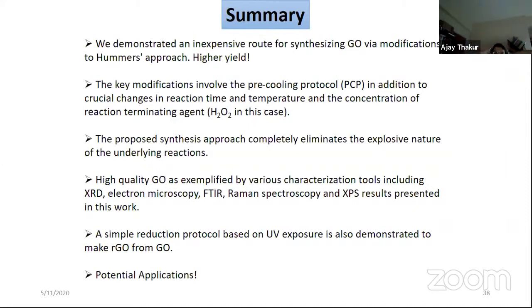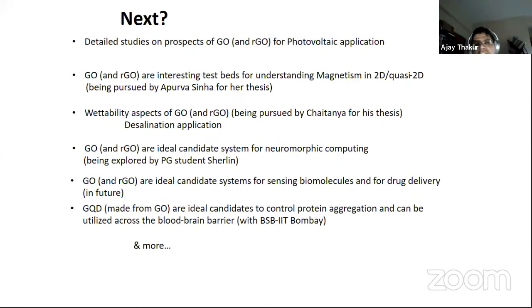Not only that, the Tour's method also employed highly expensive separation membranes or filtration membranes for preparing high quality graphene oxide. In our method, we could achieve high quality graphene oxide without using expensive filtration methods. So that made it scalable. And high quality graphene oxide was exemplified via a variety of measurements starting from XRD to XPS. And simple reduction protocols were demonstrated with potential applications.